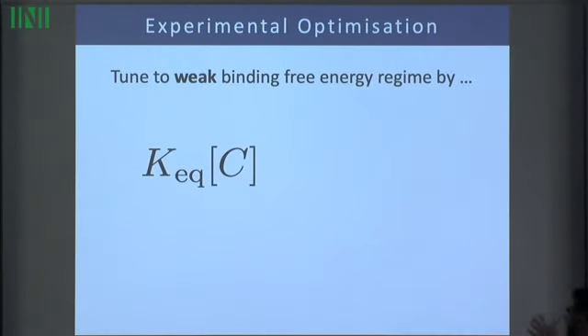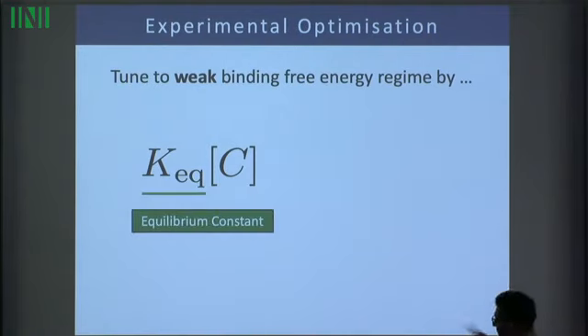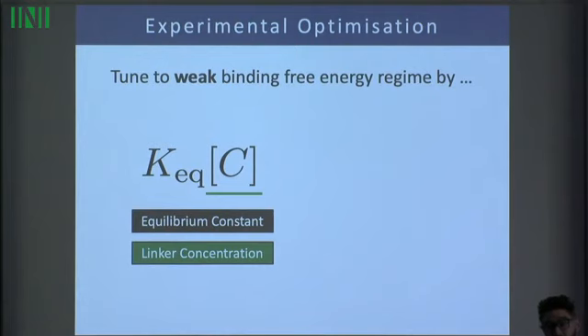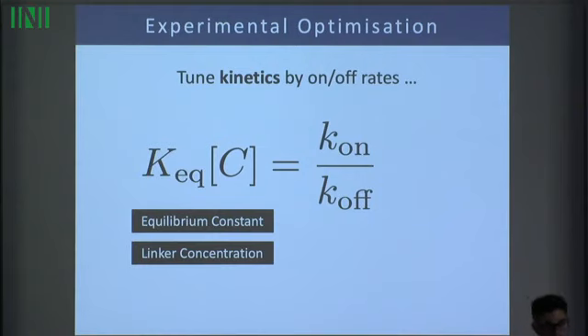And so for those of you who are not chemists, there's really two design parameters that are most important for tuning the overall binding free energy of the linkers, and this is what's called the equilibrium constant, this KEQ. And this is just the exponential of the binding free energy, actually. So we can tune KEQ, and that's actually just the chemical construction of these linkers. So we can tune the atoms that we use. That determines our KEQ. But we can also get into a weak binding free energy regime given a KEQ by tuning the concentration of the linkers. Because it's the product of those two that actually leads to the effective binding free energy that we see in this system. So we can tune that. That gets us to a weak binding free energy regime effectively. And the nice thing is that we can actually then independently tune the kinetics. Okay?